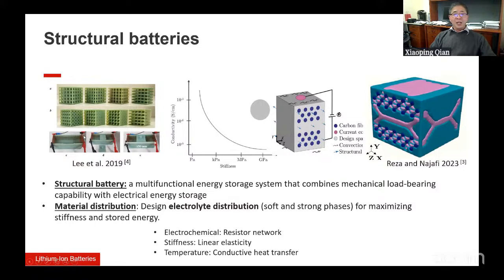For example, here in the electrolyte, you have two phases: a strong phase that has high stiffness but low ionic conductivity, and a soft phase that has high ionic conductivity but low stiffness. So how can you optimize both for multifunctionality? People have integrated linear elasticity into this optimization. Now, in this particular case, Lee used a reduced order resistor network to model the electrochemical equations. This has later been extended by Reza and Najafi, where they consider a temperature constraint. So they couple the electrochemical, elasticity and thermal equations. They formulate a multi-objective function to maximize stiffness and maximize stored energy in terms of ionic conductivity.